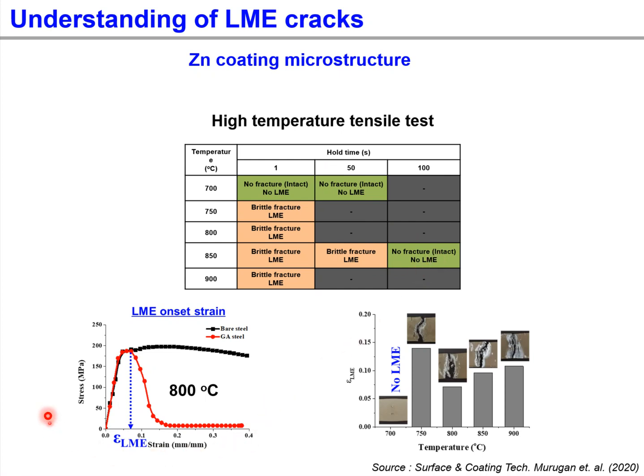The graph shows the stress and strain curve at a testing temperature of 800 degrees Celsius. The large reduction in strain with the GA-coated sample compared to the bare steel was observed due to the LME. The reduction in strain due to the LME is called LME onset strain. A lower LME onset strain value represents more sensitivity to liquid metal embrittlement. We display the epsilon LME values at the different testing temperatures. The largest reduction in strain was observed at 800 degrees Celsius, and a logical explanation is required for better understanding.